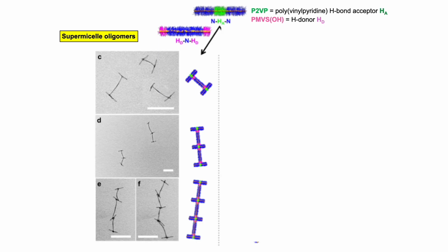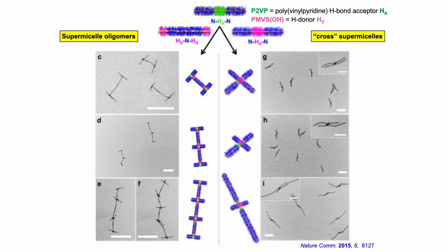You can build up block comicelles where you have hydrogen bonding acceptors in one part and hydrogen bonding donors in the other part. When you stick them together, they will actually aggregate, as you can see here. You can build elaborate structures this way. If you put a hydrogen bonding acceptor region in the middle of one fiber and a hydrogen bond donor in the middle of the other, when you mix them, the acceptor and donor regions come together and you get cross structures, as you can see here.